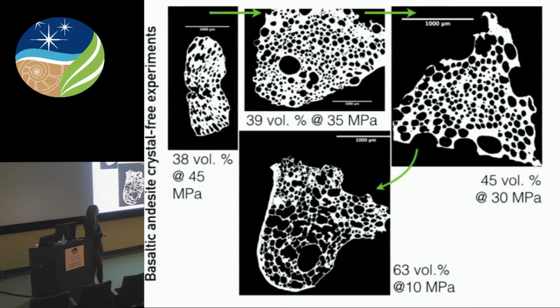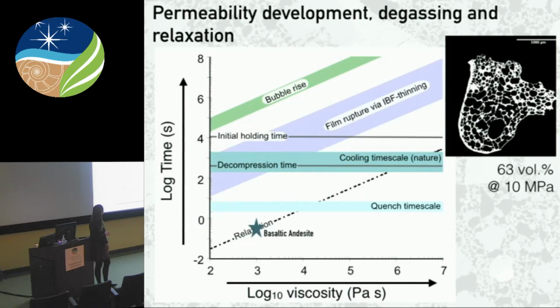Another thing we noticed with these samples is that at lower quench pressures, the vesicularities we measured were lower than what we would expect for equilibrium vesicularities. And there's a few reasons that can cause this. I realize this is a fairly busy graph, but I'm going to just ask you to pay attention to the lower half of this graph. And just pay attention to this quench timescale line, horizontal line, and this relaxation line. The quench timescale line, that's the 2 to 6 seconds I mentioned before that it takes for us to cool our samples. The relaxation timescale increases with increasing viscosity.